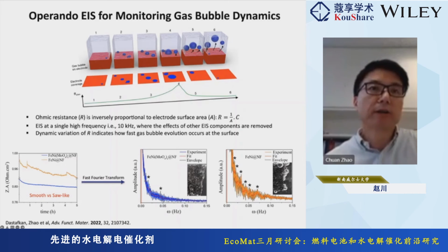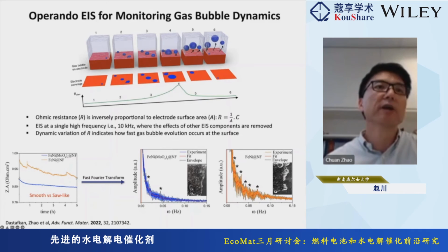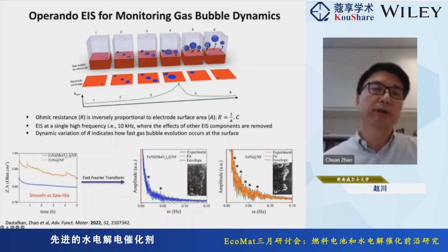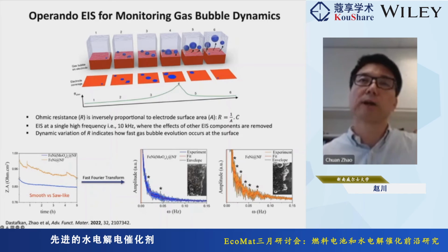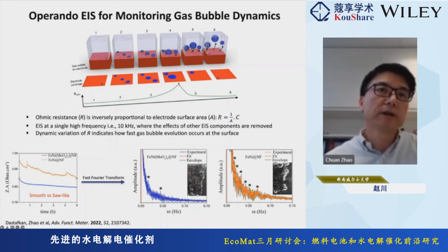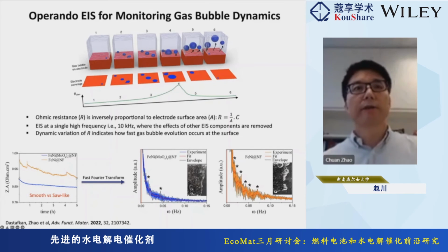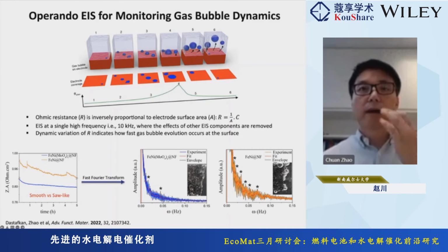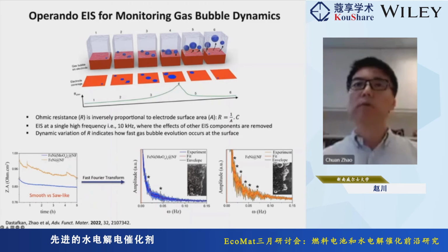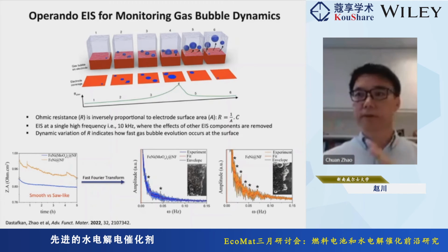Using nickel iron molybdenum as an example, with nickel iron we can see a very noisy signal. Here we don't really care about the actual value of the resistance, but really the fluctuation of the resistance. Those fluctuations are caused by the gas bubbles. In comparison, with the nickel iron molybdenum one, we see a very smooth curve. We can do a simple Fourier transform, where we get a mapping of the gas bubble evolution dynamics on the electrode over a certain period of time.